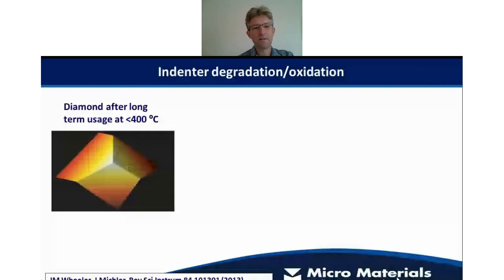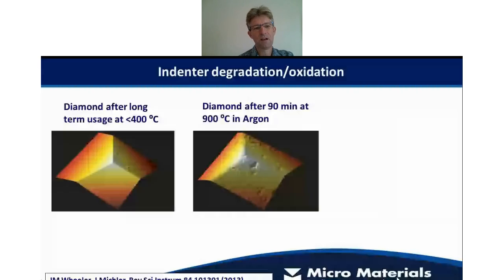So the next thing we need to worry about, as I mentioned, is the stability of the indenter material itself. So diamond is a very popular choice, and it works very well for high temperature testing as well, provided that you keep the test temperature under about 450, 500 degrees. And this is an example in this case from Cambridge University, and that's an AFM image of a Berkovich indenter. And what we can see is that it looks pretty much exactly the same as it did prior to a large amount of high temperature testing.